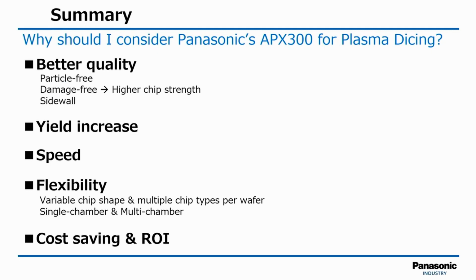So in summary, if you're a customer listening to this presentation, you should think to yourself, why should I consider plasma dicing, or why should I think about upgrading? Well, the first is better quality. It's a totally particle-free process, and as I said, no mechanical damage, which leads to higher chip strength. And if you have very high-value products, for example sensor chips that are very expensive, maybe you can have huge gains by providing much better quality to your customers with much cleaner and damage-free sidewalls. If your devices are small, you can definitely increase your yield. This is without question, going down, as I mentioned, to 5 micrometers dicing street width.